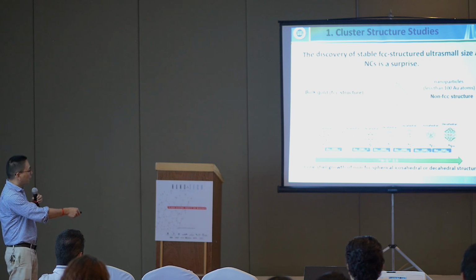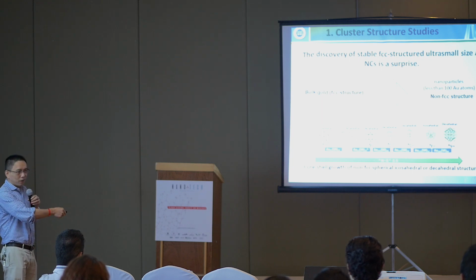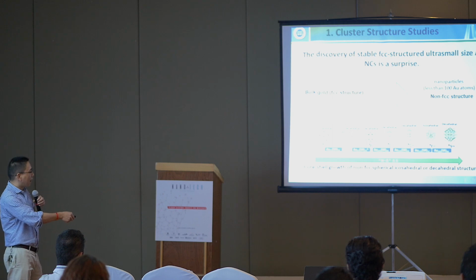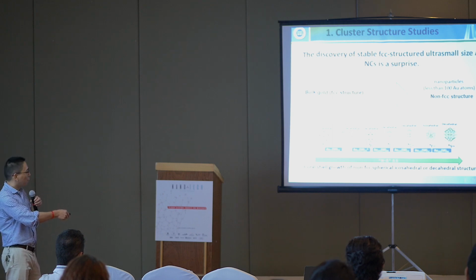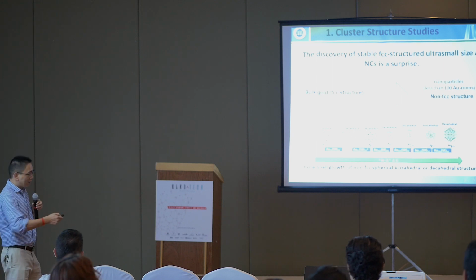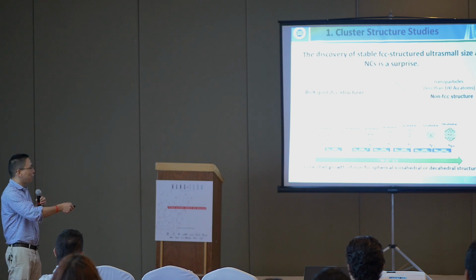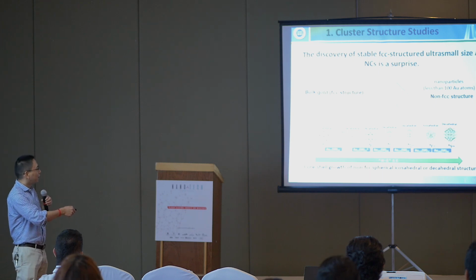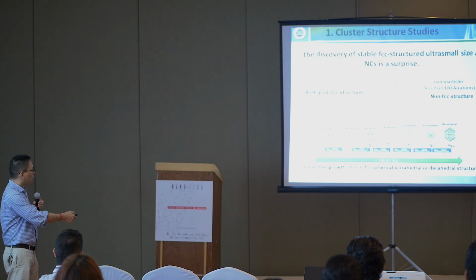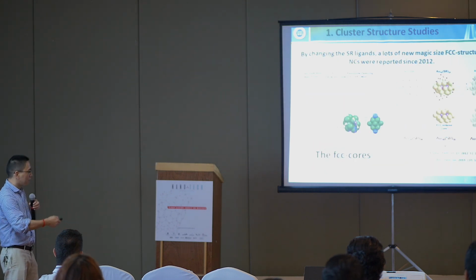So usually we know the evolution of ligand-protected gold clusters. They grow gradually shell by shell, and they form a cluster of polyhedral structures. But this is the first time we find FCC structures in these three examples.